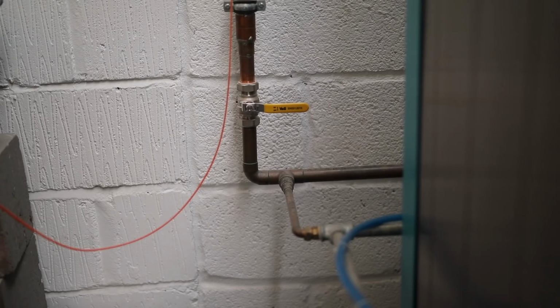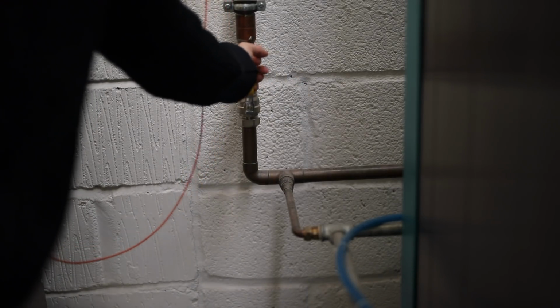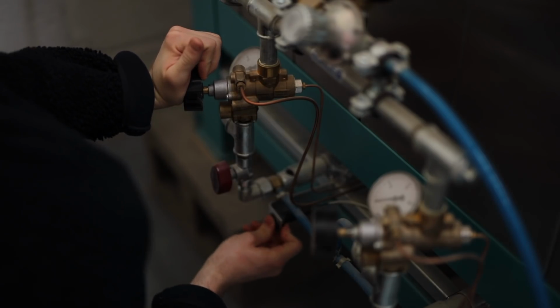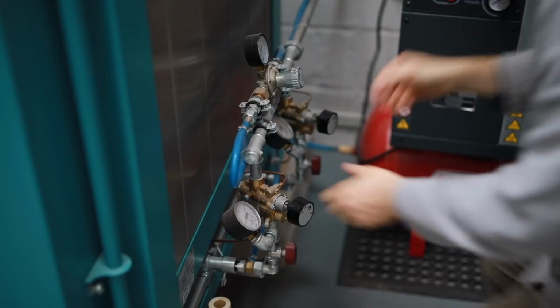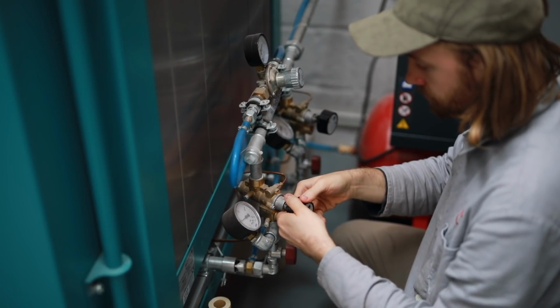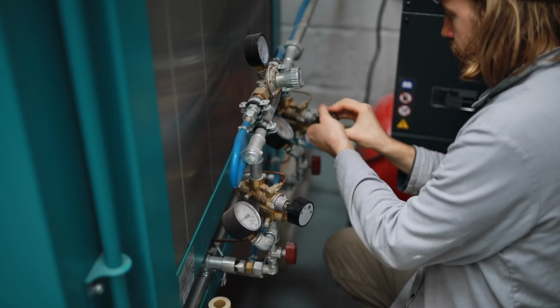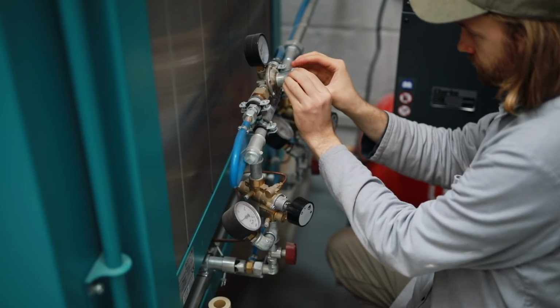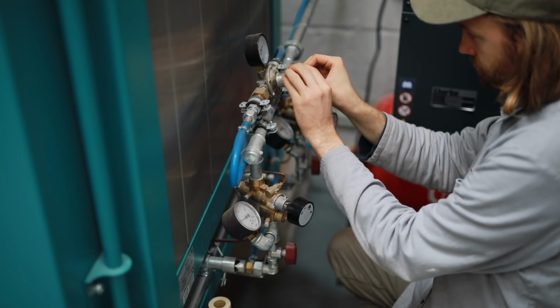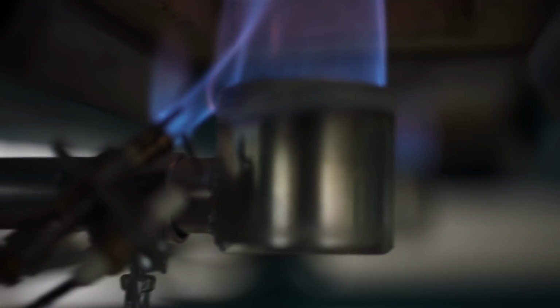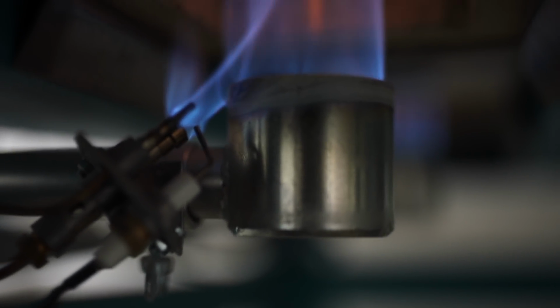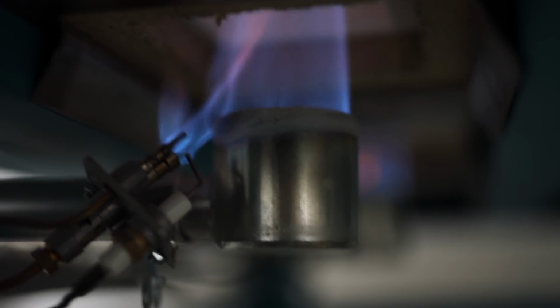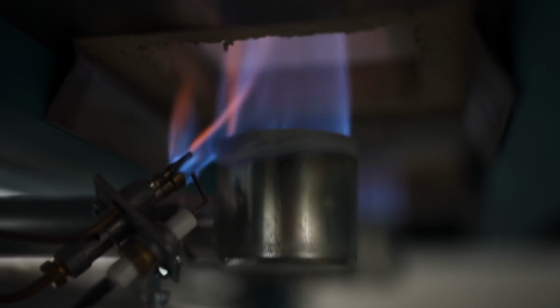Usually very early the next morning, I switch on the gas and ignite each of the 4 burners, making sure that the door of the kiln is open during the lighting process. That way there's no risk of gas accumulating in a closed chamber and then being ignited, which can and does lead to explosions and injury. Once ignited and the doors are closed, I very gradually, over about 5 hours, take the kiln up to 860 degrees Celsius. This is the point where I initiate reduction, and this is also what's responsible for the green hues in my glazes.